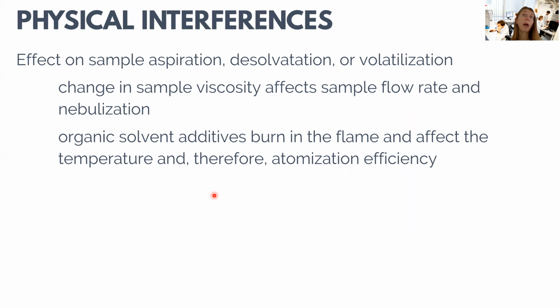For example, if the sample has very different viscosity than do the calibration standards, then the flow rate of the sample is going to differ from sample to standards, and therefore we will not see actually the same concentration of the atoms in the flame. Also, for example, if our standards are neat water solutions, but our samples contain organic solvents, then these organic solvents burn in the flame, and by this process they also affect the temperature of the flame. And of course, temperature is affecting the atomization efficiency as well as the excited state to ground state ratio. So if we have this fluctuation in the temperature due to the sample content, then we also have differences in the atomization efficiency for the samples.